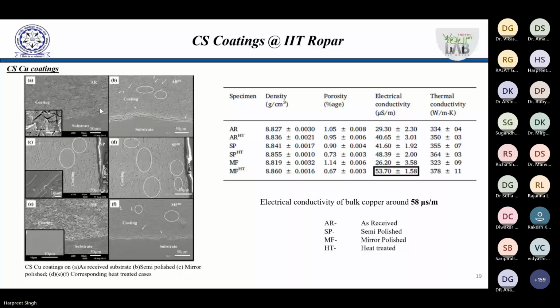So then we took it at IIT Ropar, and of course with the help of our IPR, the funding, and then we could deposit these coatings, right? It was a challenge actually. The copper, first thing, it has to be pure. Another thing, it has to be deposited on stainless steel, which is a hard material, right? So copper on stainless steel, this was a challenge, how to get a good adherence, right?